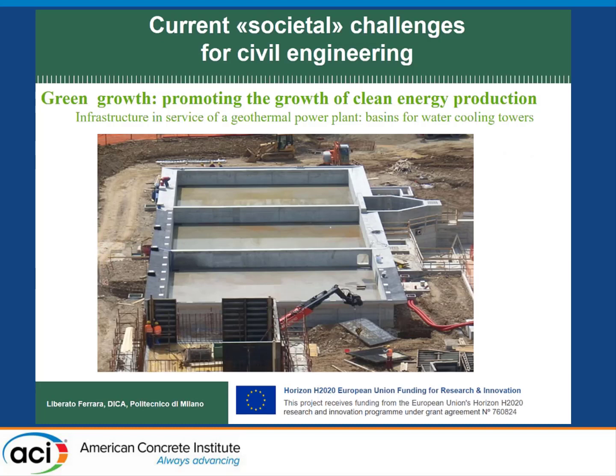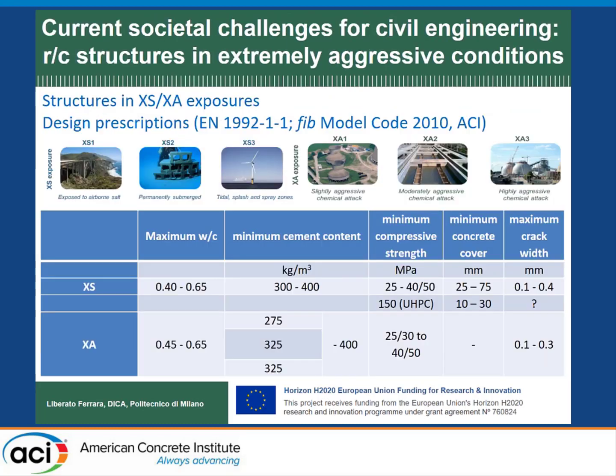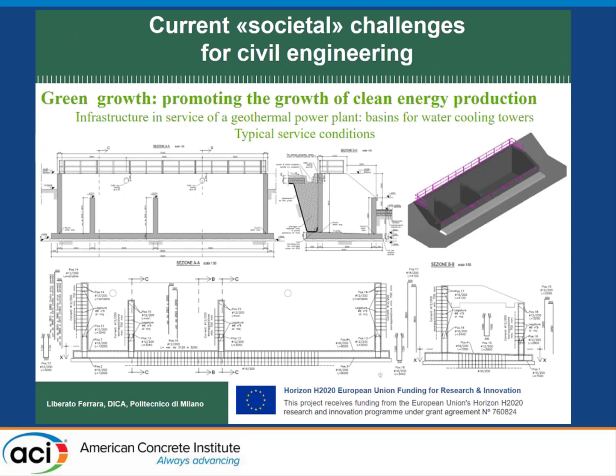The simplest of them are the basins that are in service of the cooling towers for the water, which is part of the geothermal drilling and then has to be reinjected into the ground in order to avoid soil settlement. So this is a typical example of this structure, which obviously has to be designed complying with the conditions for durability for extremely aggressive exposure, because the water that the structure has to contain actually contains chlorides and sulfates, and these aggressive conditions are labeled as XS and XA in the Eurocode and the fib Model Code. This is a typical design, not much reinforcement, but the issue is that because of the durability issues, these walls have to be made 40 centimeters thick in order to comply with the requirements. So there is quite a huge burden.